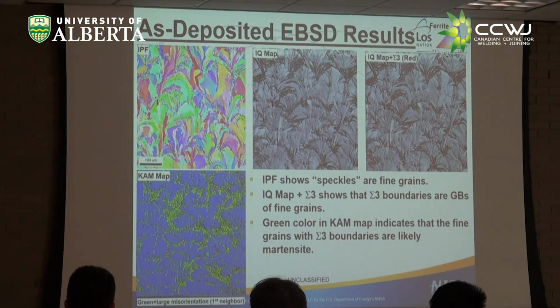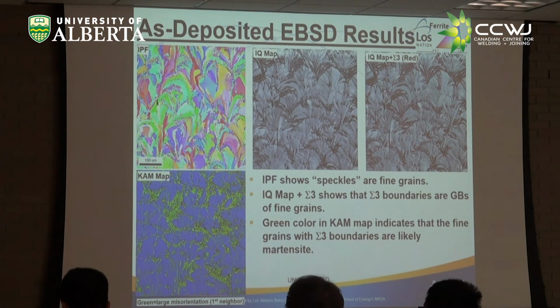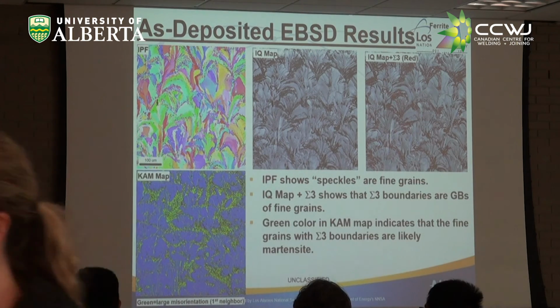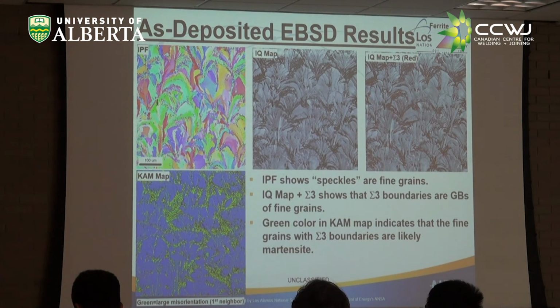So the irradiation tolerance, I should explain. Actually, let me go stand at the microphone. The improved radiation tolerance occurs because the lath sites in the martensite act as sink sites for the damage, the vacancy and the interstitial, carbon, substitutional. There's also hydrogen, helium, a daughter product formed. So the martensite lath boundaries are what really help you with that, because they're low angle sigma 3 boundaries. They will act as sinking and trapping sites and recombination sites.